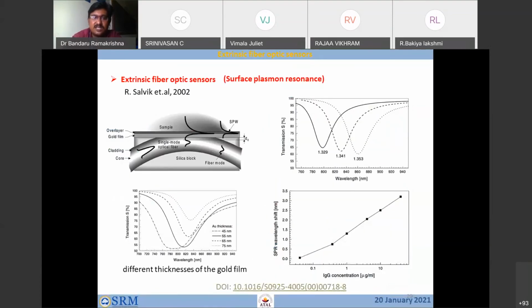Let's look at one technology here. The fiber is sliced slightly and coated with a gold film, and then a TiO2 film is given there. Now you see that if there is any change in refractive index on the coating, the absorption characteristics of that gold film change. When the refractive index changes from 1.32 to 1.35, the absorption characteristics of the gold change, and that can be recognized by the fiber. Likewise, why don't I use a coating on this gold nanofilm and then go for a biosensing application? Yes, we can do that.